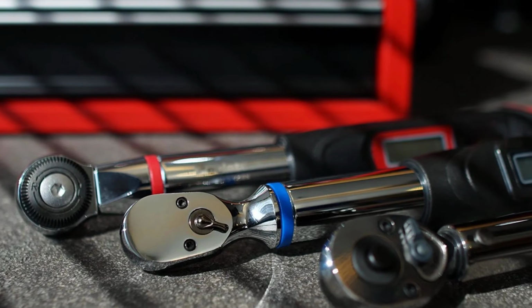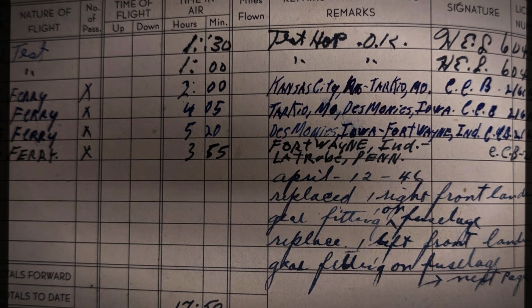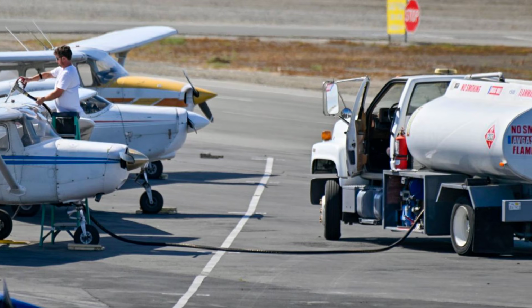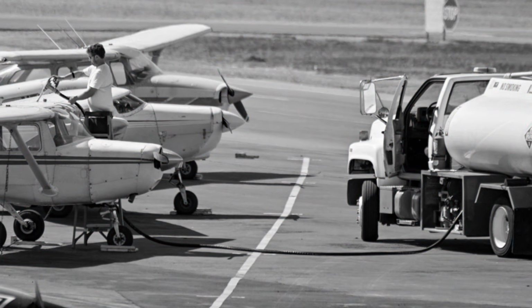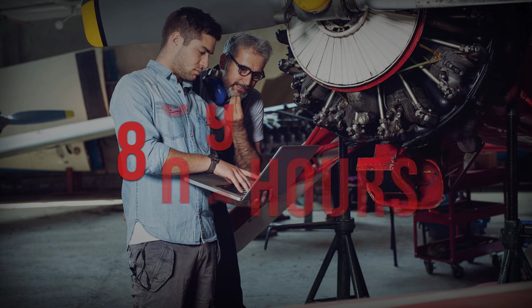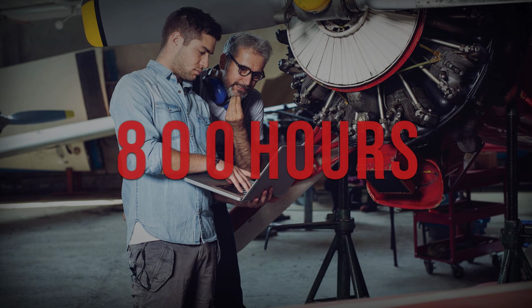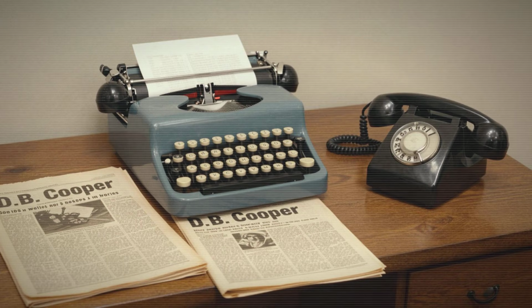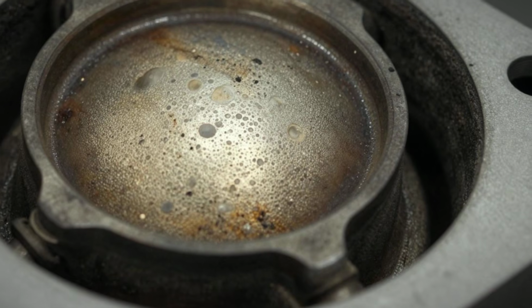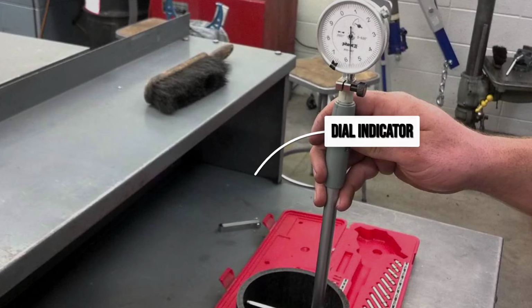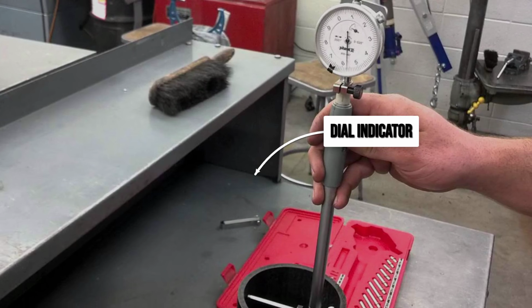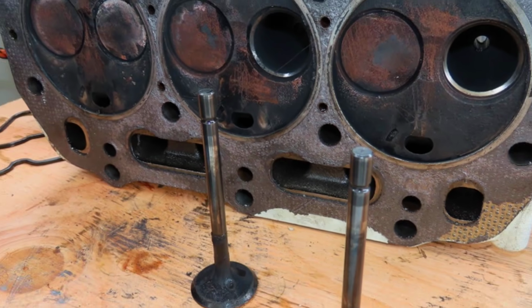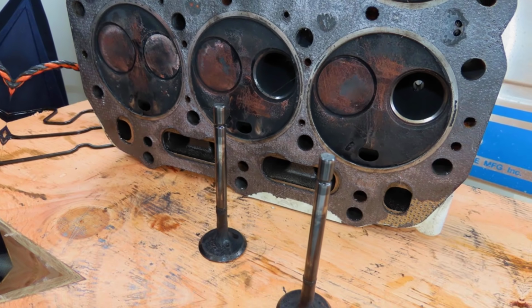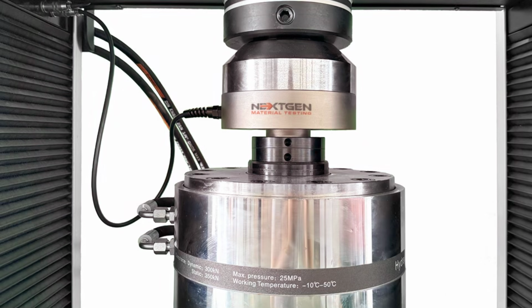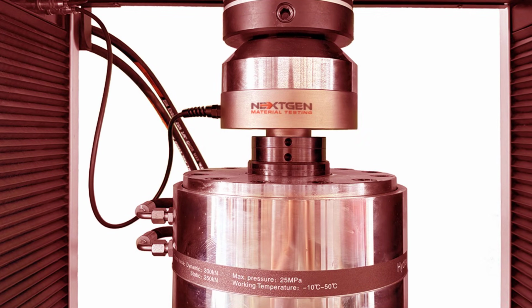Step 2. Overhaul the inspection rhythm. The old 1,200-hour top-end schedule is a luxury of the leaded era. In the solvent shadow, every 800 hours is a new line on the calendar. Lap the valves, bore scope the seats, measure the margin. If the contact band shows pitting or the margin thins past 40 thousandths, pull the cylinder. Physics does not care about FAA paperwork or environmental optimism. It cares about contact pressure, heat, and time.